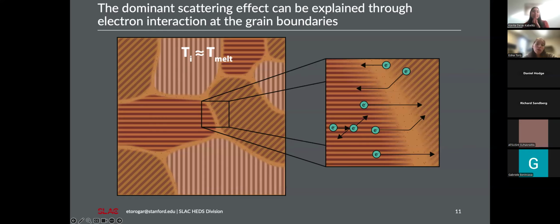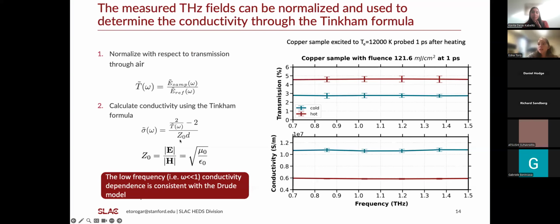This was a problem for us for some time because we were not aware of this type of change, and as you notice, our conductivity is obtained by doing some sort of division over the thickness. Let me show you the equation. This was giving us some trouble. Our films were originally about 30 nanometers, so a 10 nanometer deviation is a lot. Because we are dividing over the thickness, that brought us a lot of problems.